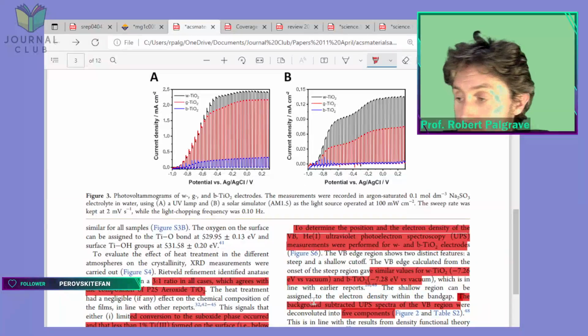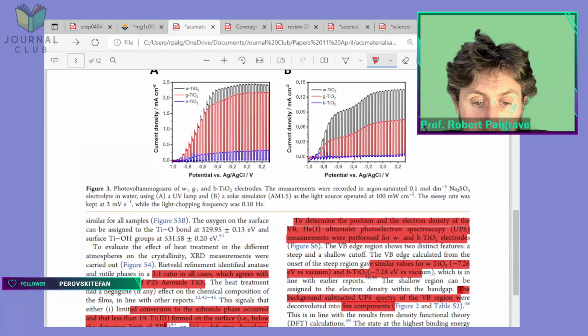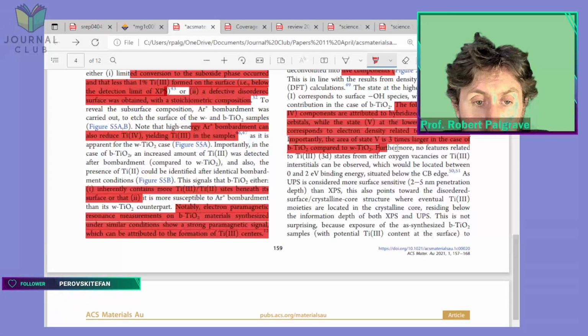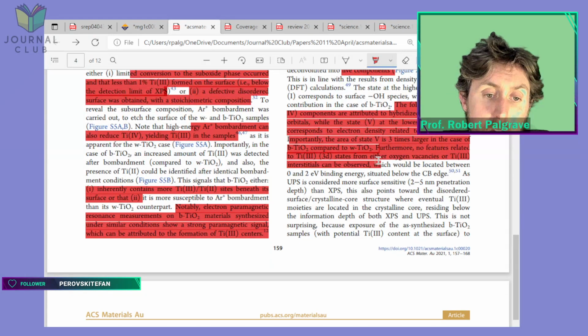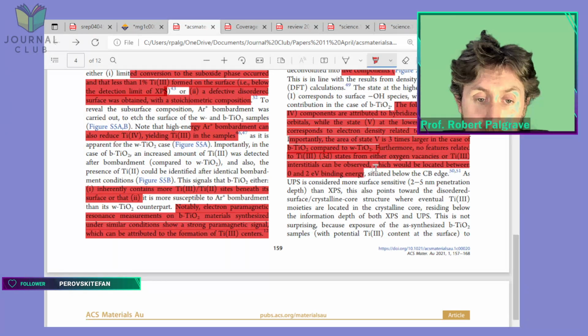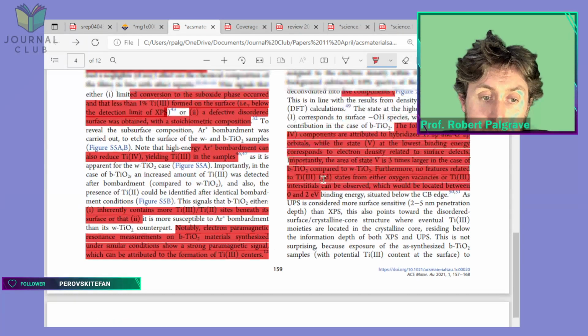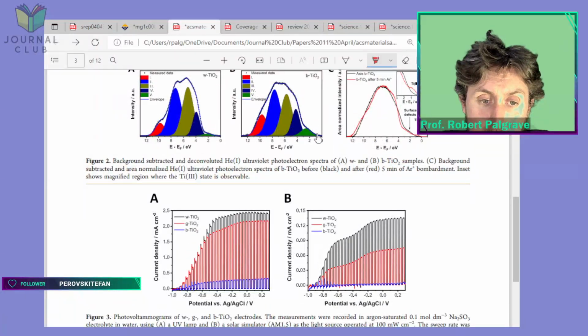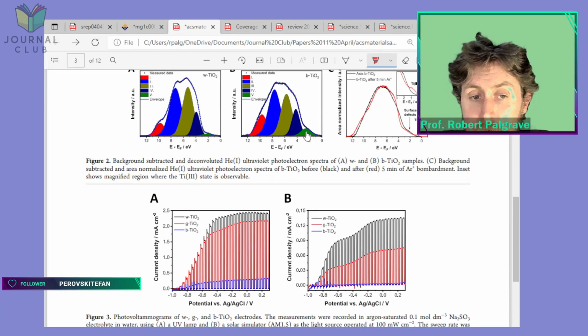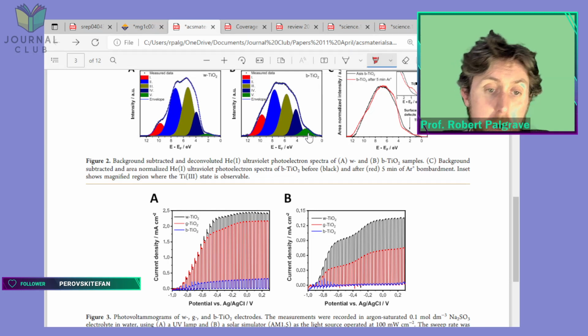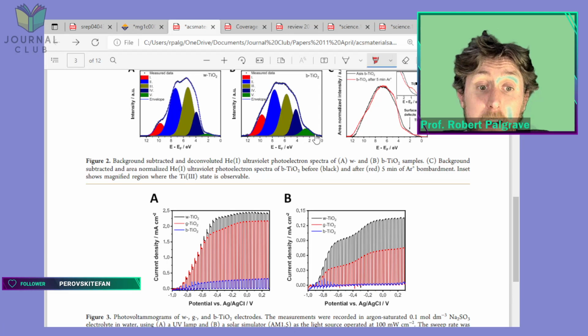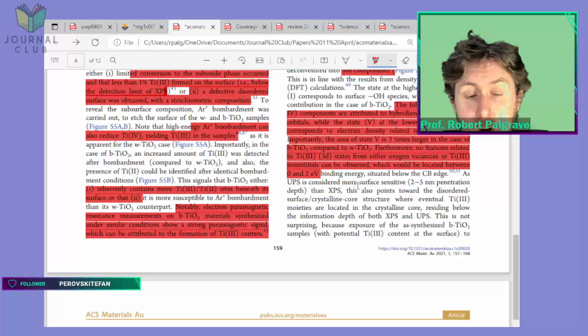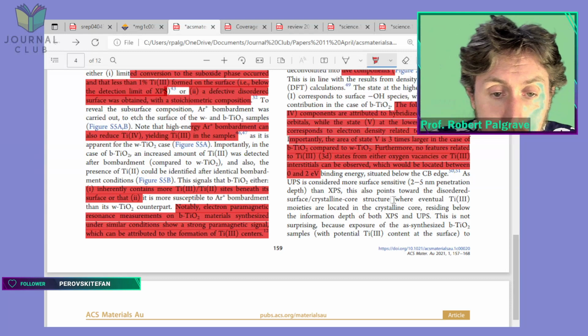But let's continue anyway, because we're making slow progress at the moment. So. Furthermore, no features related to Ti3+ 3D states from either oxygen vacancy or Ti3+ interstitials can be observed, which should be located between 0 and 2. Okay, well they're kind of contradicting me. They may well be right there. So nothing between 0 and 2. Well, there is this kind of thing here, but they've assigned all this intensity to this component just above 2. But there is something there. So I don't think it's completely definite that it's definitely not Ti3+, but combine it with the XPS results, which didn't detect any Ti3+, maybe that makes some sense.